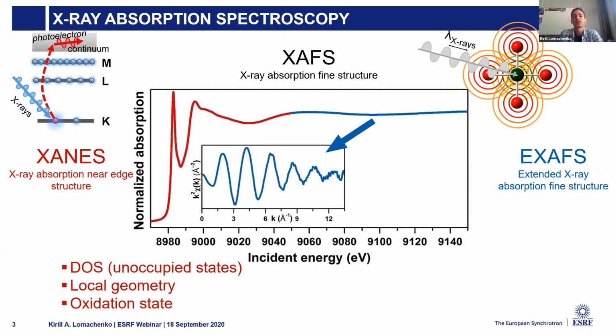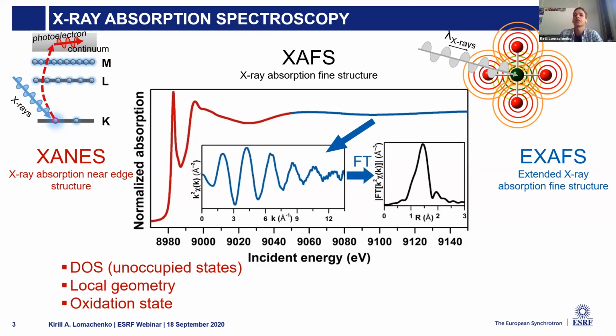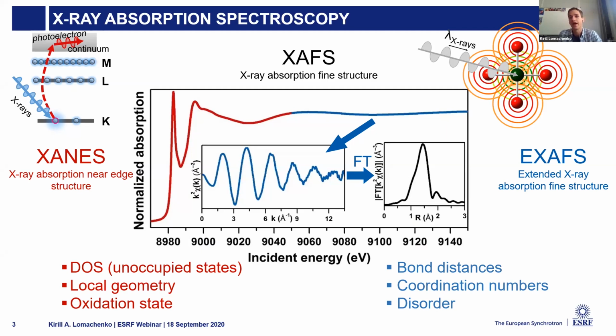When this signal is Fourier transformed, we get something similar to a radial distribution function. It's not exactly a radial distribution function, but it's pretty similar, and it contains information about bond distances, coordination numbers, and disorder.